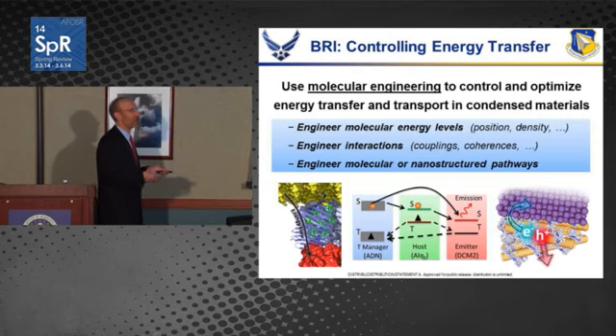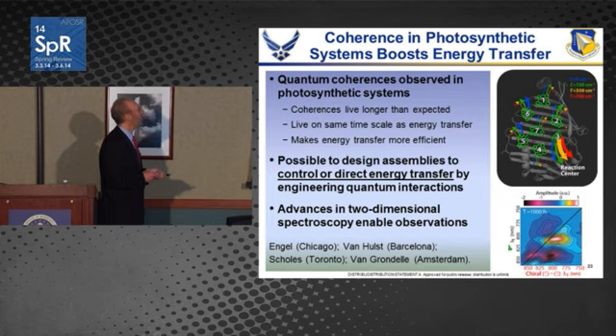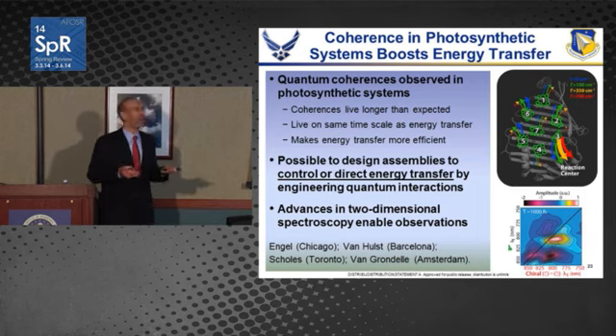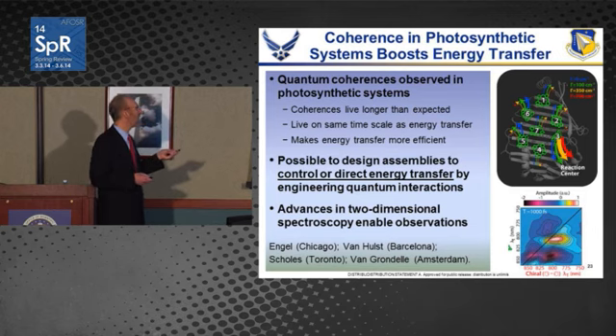Nature can do that very efficiently, 10 to 1,000 steps with 100% transmission efficiency. We'd like to know if we can do that. One way that we've seen recently is that natural photosynthetic systems have been demonstrated to exhibit coherences. These coherences have been observed to live much longer than expected, for picoseconds or so. What's important is that they live on the same time scale as the energy transfer processes.